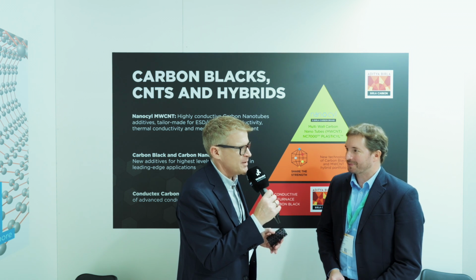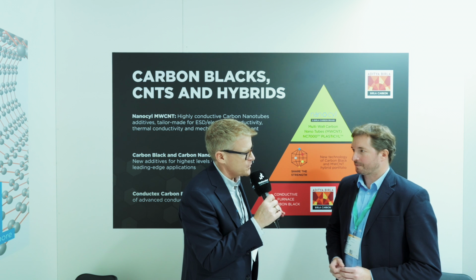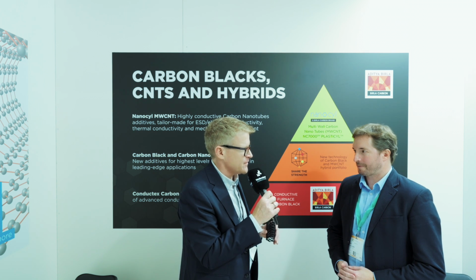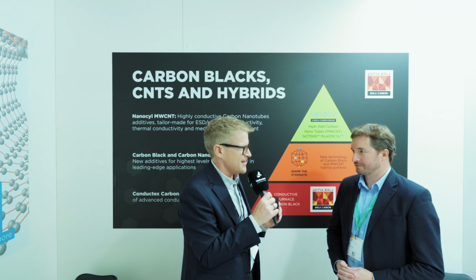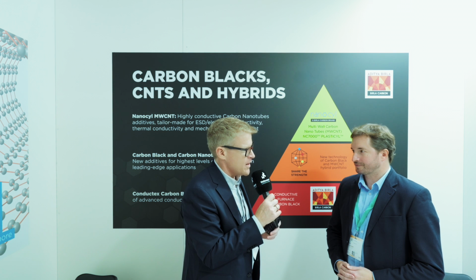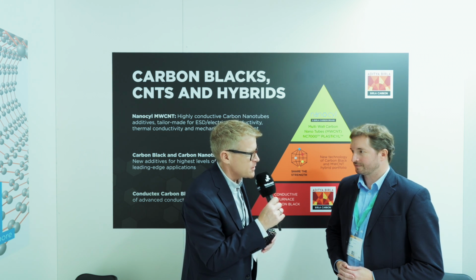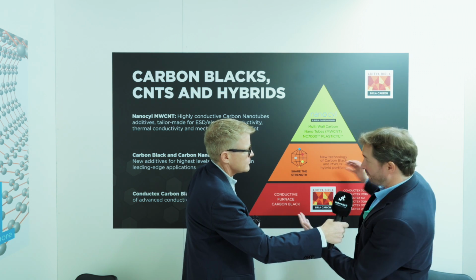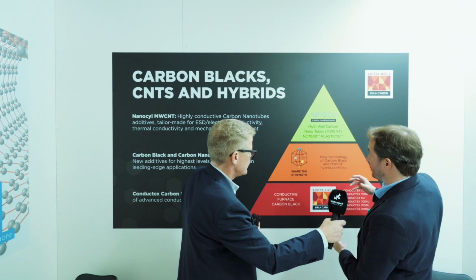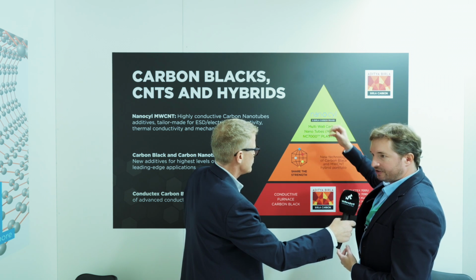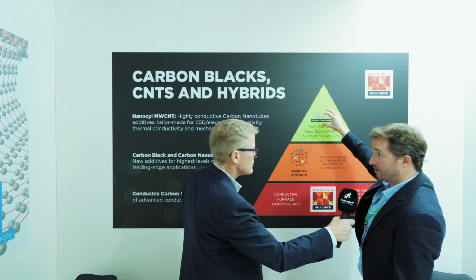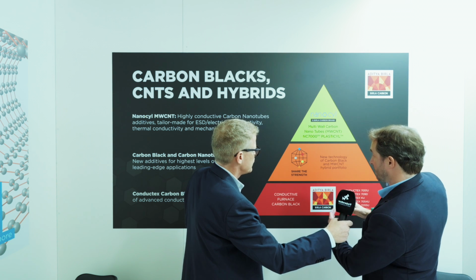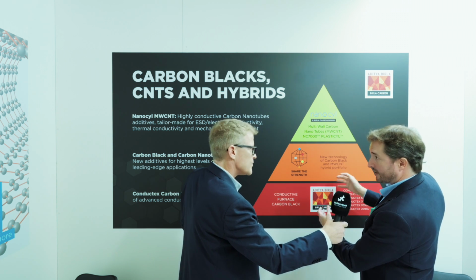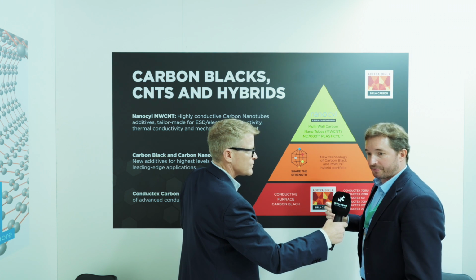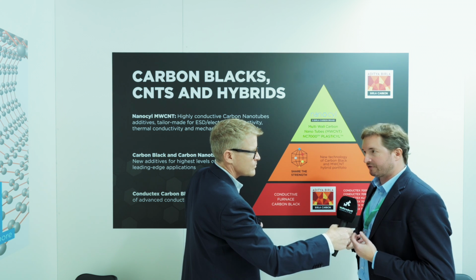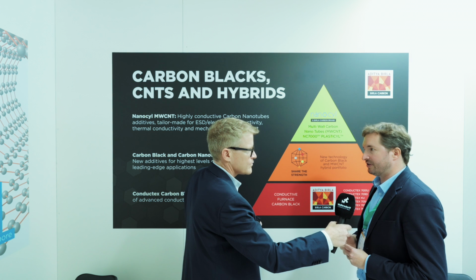Just out of interest, Cedric, where do you position multi-wall carbon nanotubes for conductivity along with graphenes and maybe highly structured furnace carbon blacks and single-wall nanotubes? Where's the advantage of multi-wall nanotubes from Nanocyl? So, basically you have this type of pyramid, which shows the complexity of the material and the ability to get a higher range of properties. Multi-wall carbon nanotube will be at the top of this pyramid compared to standard conductive materials, highly structured carbon black, and graphenes, and carbon nanotube will come on top. Meaning that you would really need the lowest amount of carbon nanotube in order to reach this electrical conductivity.